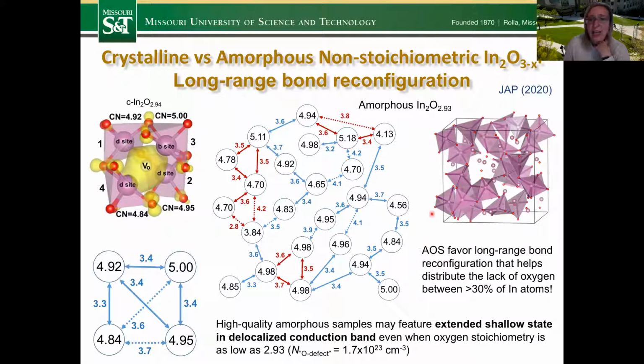Yet as we go to amorphous, this big network of undercoordinated indium atoms, the 30% as I mentioned to you, they share the lack of oxygen with each other. So because of that bond reconfiguration and weak bonding and rearrangement, the vacancy looks like that. It's an extended state, and actually we have a shallow and delocalized conduction band, even when the oxygen stoichiometry is as low as 2.93, so below 3. It's a large oxygen defect concentration, but still we end up with an extended shallow state in what we call high quality amorphous samples with delocalized conduction band.